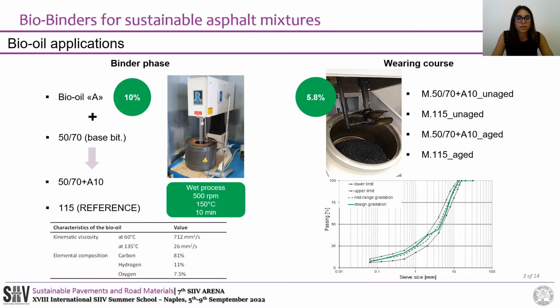A wood bio-oil, coded as A, was dosed at 10% by weight to replace a conventional 50-70 penetration grade bitumen. Some characteristics of the bio-oil are listed in the table below, such as the kinematic viscosity and the elemental composition that makes it compatible with bitumen.